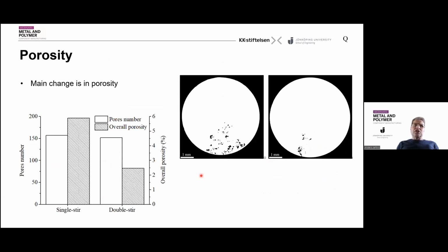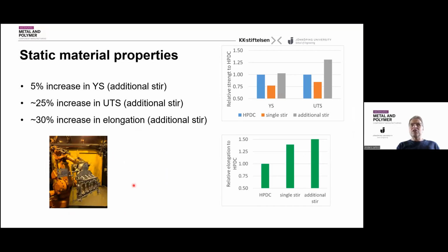Now, one thing that was up for discussion is also porosity. As you know, when you talk about porosity in commercial size materials, you have relatively large porosity level. And in this case, it was a full-scale large component. And with the single stir process, we had up to 6% porosity in the regions that we were investigating. And we also looked at the pore numbers, so the number of pores per unit area here. Now, when we did the double stir, we actually didn't really change the number of pores, but we significantly reduced the overall porosity. And this is, of course, not surprising, because when you look at the extension here, if you halve the porosity, then of course you get better elongation.